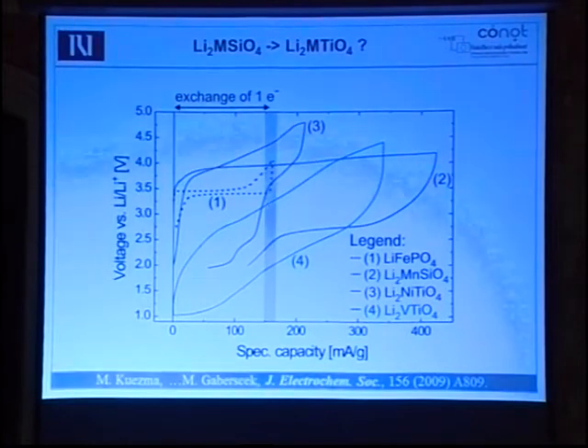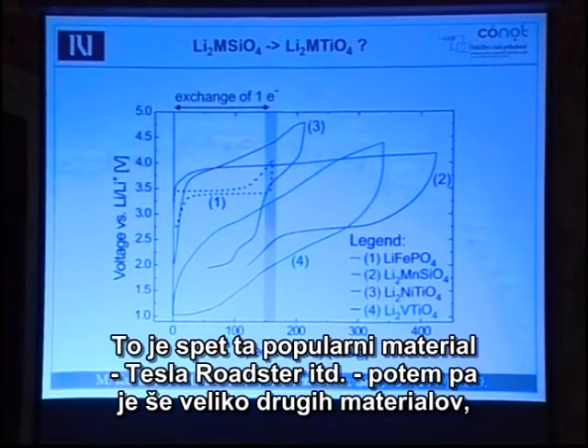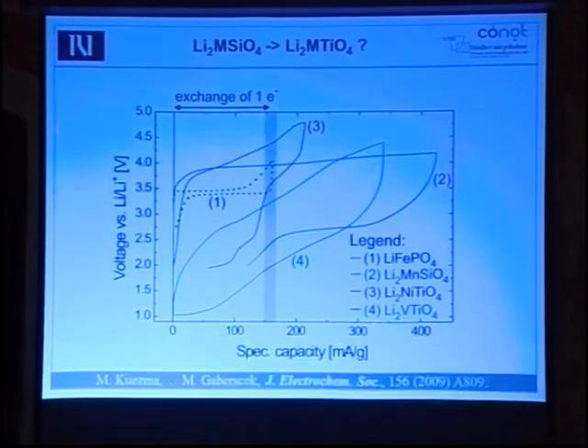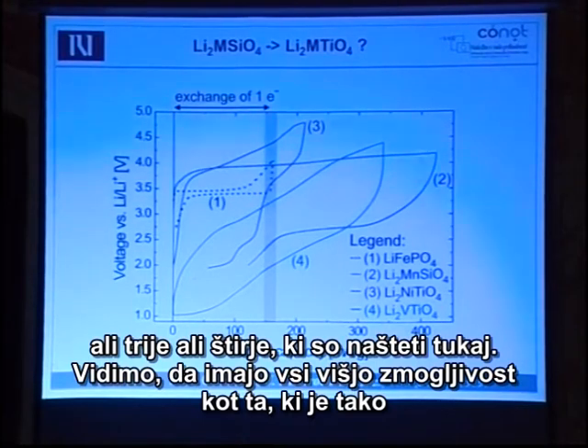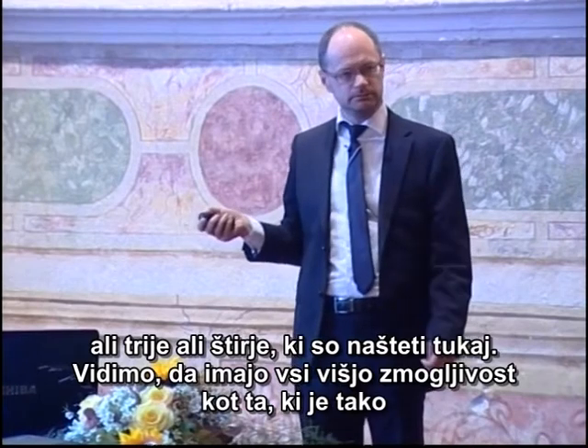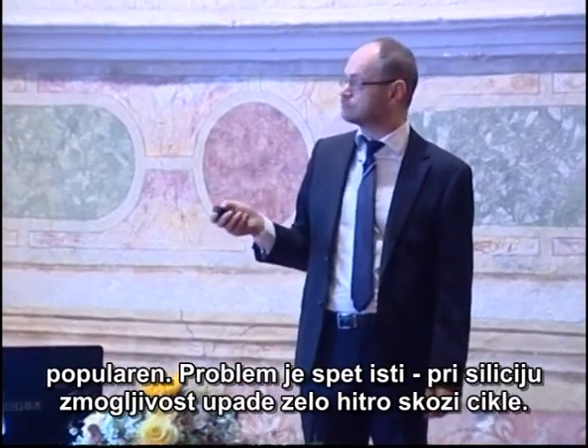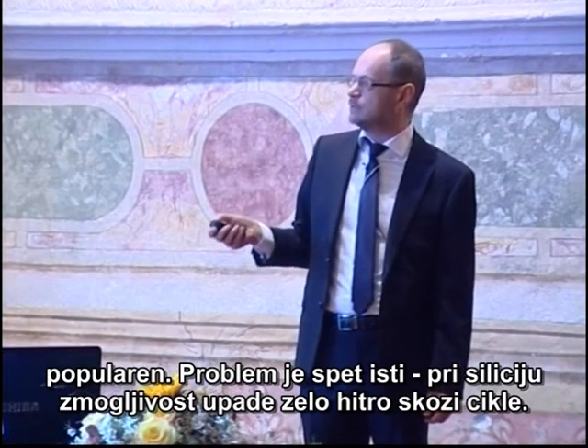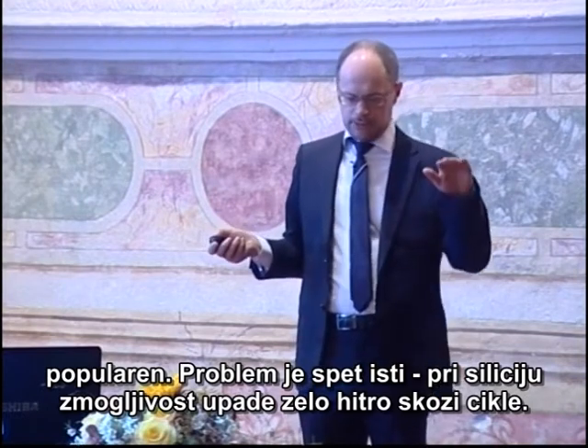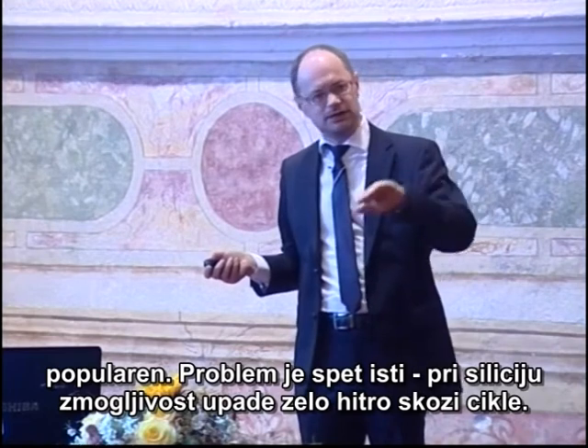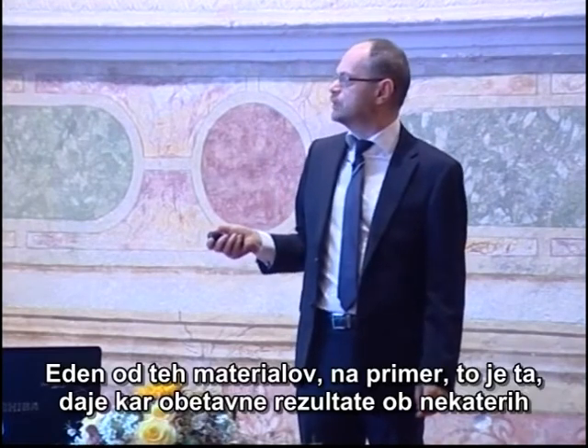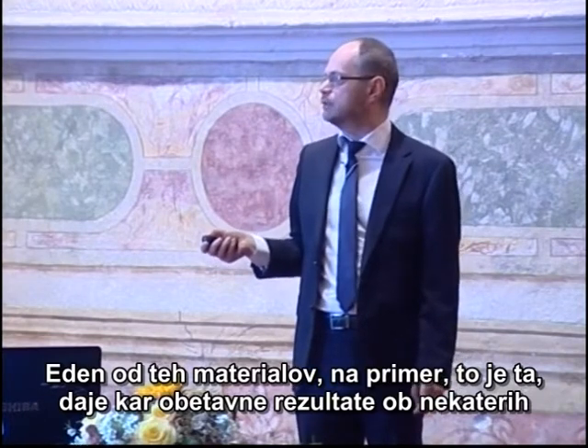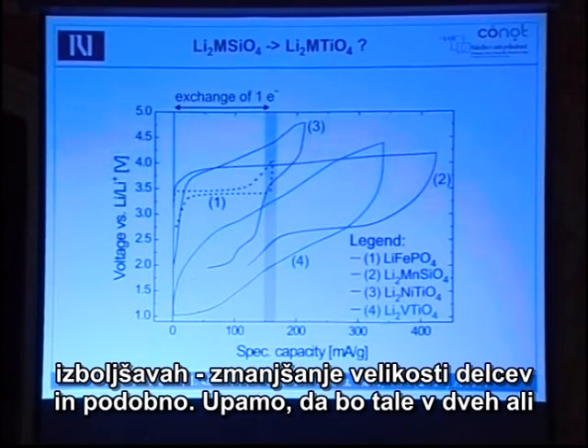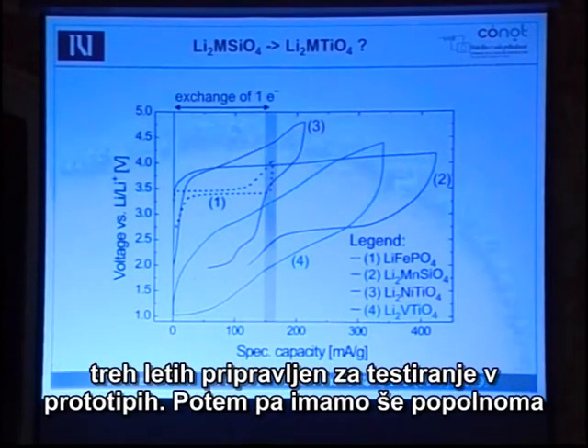Okay. So this is again this popular material for, in Tesla Roadster and so on. This is the capacity, the gray zone. And then there are many other materials, or 3 or 4 of them, which are stated here. And you see that all of them have better capacity than this popular one. Again, the problem is the same one as with silicate. The capacity drops quite fast with cycling. One of these materials, for example, this one, shows quite promising results with some improvement, decreasing particle size and so on. And we hope that this one can be, maybe in 2 or 3 years, prepared for testing in prototypes.